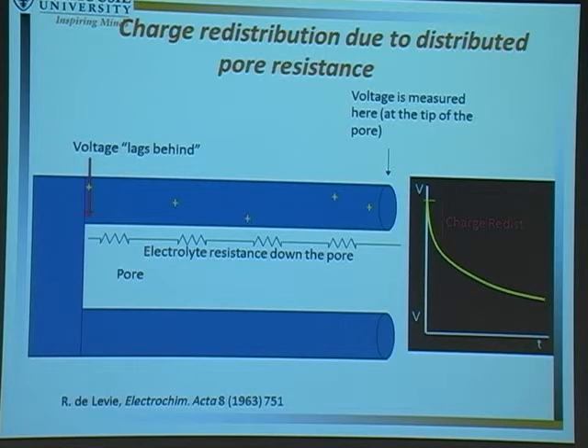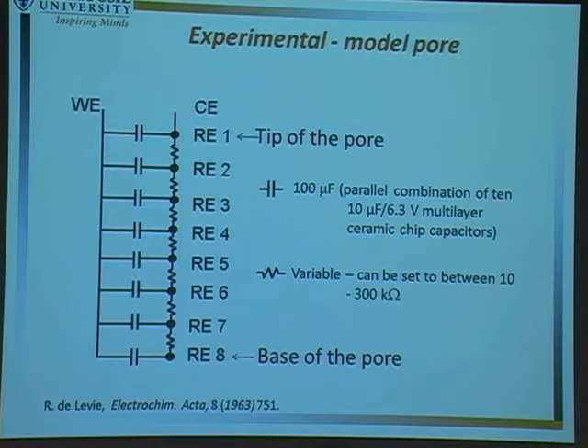So when we identified this, what we said was, okay, well, likely this charge redistribution is very rapid. Other people in the literature had said charge redistribution takes about 100 seconds. And then what we expected was, if this is charge redistribution, we can deal with everything after this to talk about the Faradaic self-discharge. So what we wanted to do was actually model to make sure this is true. And the way we did that is we built a transmission line model based on de Levie's seminal paper from 1963, where he's talking about how the pore acts as a transmission line. And again, that means that you're charging the tip of the pore more quickly than the base.